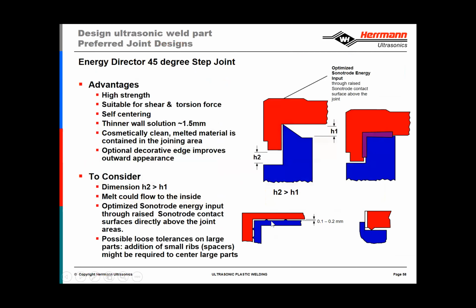On the previous slide, as well as on this slide, we showed these ribs. If you have issues with centering the part, ribs can be added perpendicular and in this configuration along here to make sure that the blue part is centered within the red part. So that's what these graphics on this slide and the previous slide were showing.